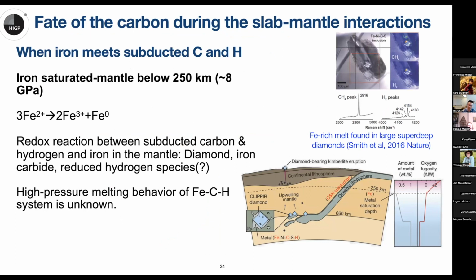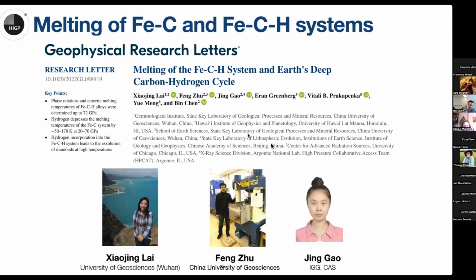There is recent work about diamond inclusions, the iron nickel carbon sulfur inclusions in super deep diamonds. That's an indication that during the formation of those diamonds, metallic iron may be involved during the formation of the super deep diamond. So the redox reactions between the subducted carbon or hydrogen and the iron in the mantle may be responsible for the formation of the diamond, in the transition zone or deeper. In this work, we determined the melting of the iron carbon hydrogen system by laser heated diamond anvil cell.